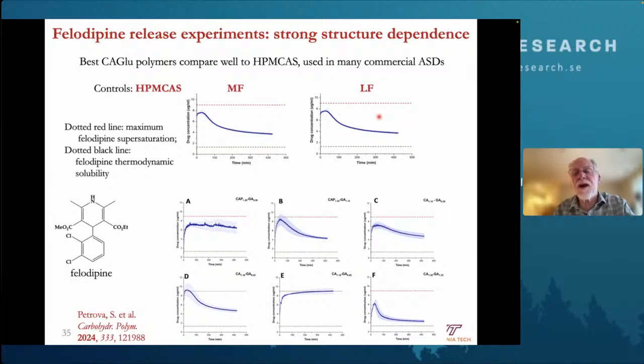Okay, so these are the two grades of HPMCAS, amorphous solid dispersions of felodipine. You put it in, get a burst, high concentration, but then within a relatively short period of time it starts to crystallize, and therefore you lose soluble felodipine. So it's helping, it's definitely helping, but it's not performing exactly the way you'd like it to.